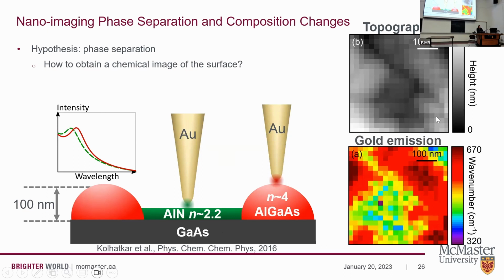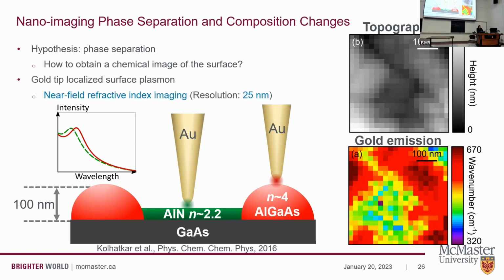So we can see that we got a very good correlation between the two, where the red regions correspond to the islands, and the blue-green regions correspond to the pits. Now when we go from the top of an island to a pit, we can see a shift toward the lower wave numbers on the gold emission, which indicates a decrease in the refractive index between the two media. And this image was obtained with a very high spatial resolution of 25 nanometers.